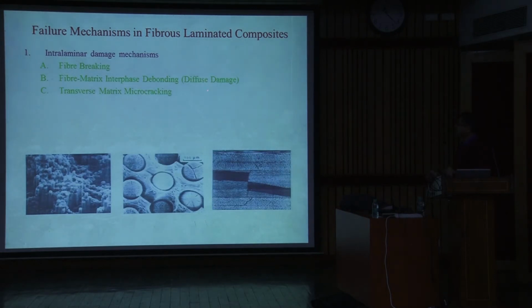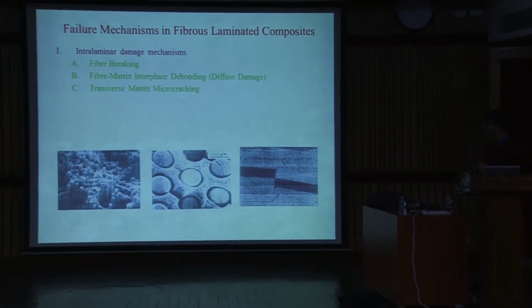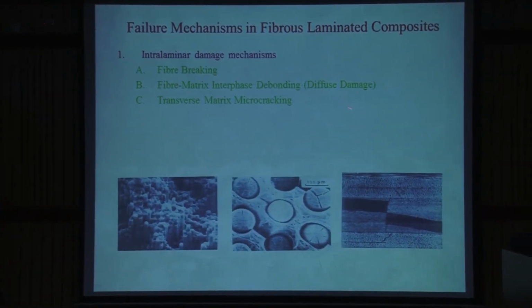Again, as I said, intralaminar damage mechanism. So what are the possible things? One is that you can have the breakage of fibers. This picture shows that the cylinders are nothing but the fibers, and you can see that these are broken fibers. Then you have fiber matrix interface debonding or diffuse damage. This is the micrograph which shows the fibers. These circles are the fibers, and this is the matrix material. The bond between fiber and the matrix becomes weak, and there is a failure. This is called diffuse damage.